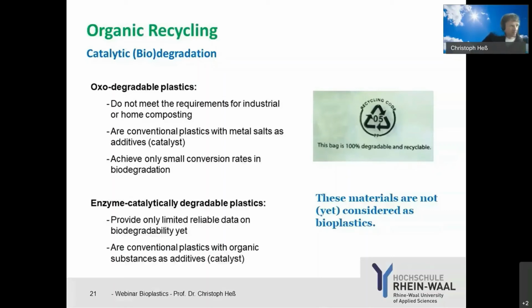We also have to talk about another degradation issue that has created heavy discussions for many years now, and that is the catalytic degradation of plastics. We have, for example, so-called oxo-degradable plastics, and there are suppliers that claim these materials to be also biodegradable. Sometimes they say this is bio-oxo-degradable. But that is not the same as a conventional biodegradation according to the standard EN 13432. What they do is put catalyst material in a conventional plastic like polyethylene, and that starts to degrade by oxidation. That accelerates oxidation of the polymer, so the plastic will fall apart into very small fractions, sometimes almost invisible. But that does not necessarily mean that there is also biodegradation. In biodegradation, only small conversion rates are achieved.